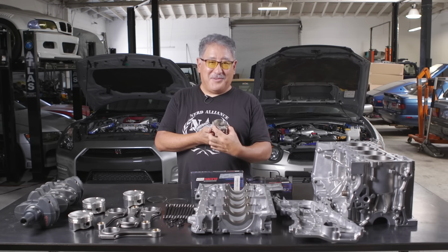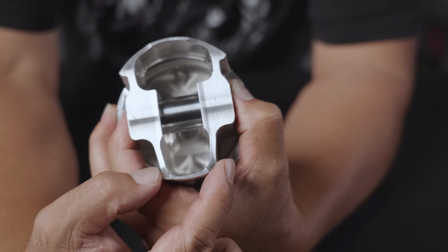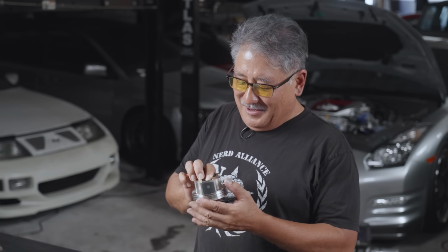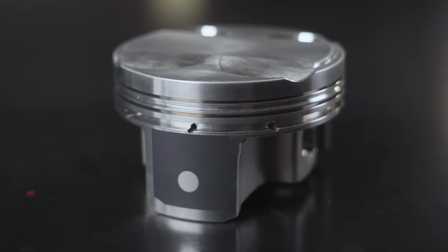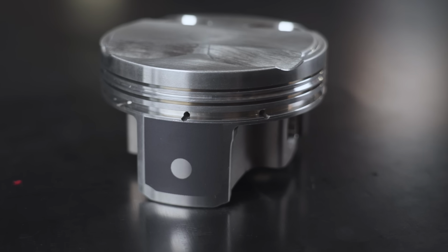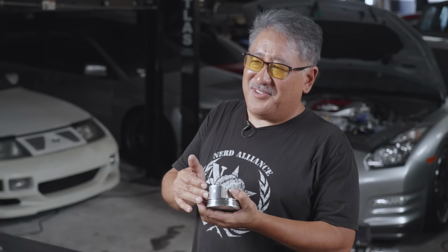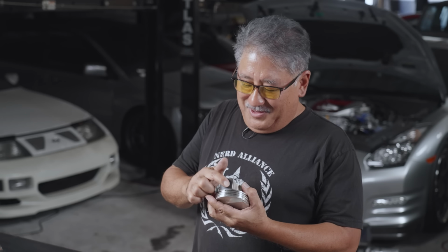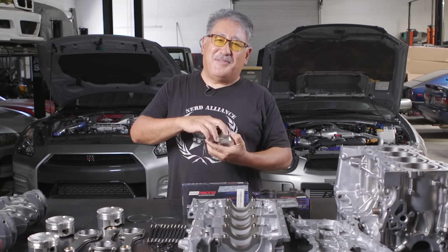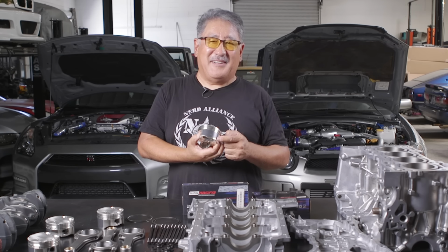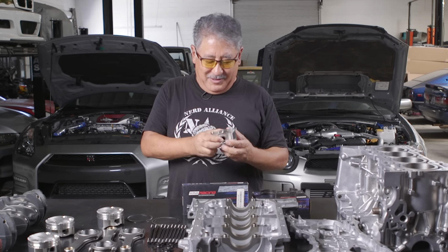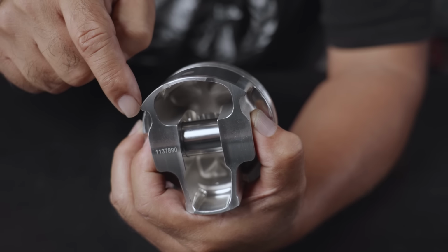One of the things you might notice first is an asymmetrical skirt. A lot of race pistons have what you call a slipper skirt, a really small, minimalized skirt that's cut down to the minimum. This gives the lightest weight and least amount of friction, but there's a lot of point loading and a lot of wear. So the JE piston on the thrust side, the side that sees the most load, is way wider, almost as wide as a full skirt piston. This spreads out the load, reduces wear, and reduces rock in the bore, which can make piston slap noises. Basically, you get the best of both worlds.